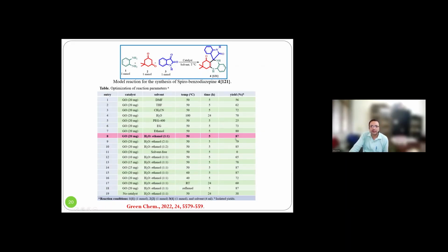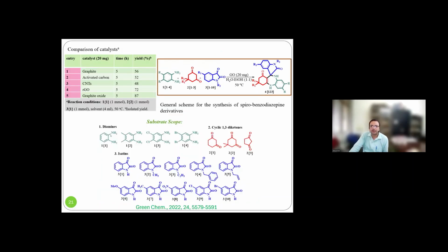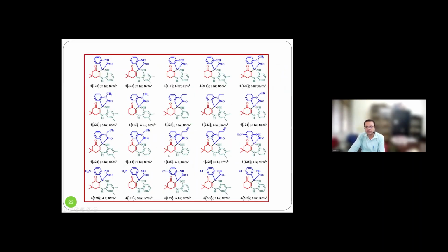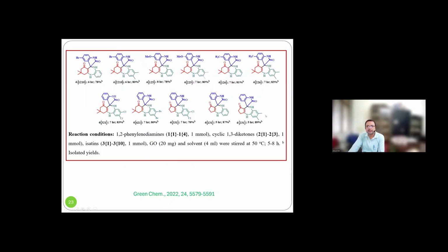So actually what we did, we tried it: ethanol is giving a good result also, but the water ethanol mixture is better than ethanol. Then we explored various derivatives here, various diamines, various isatins, we examined, and various 1,3 diketones, and we made, I think, more than 30 derivatives here with good yield.